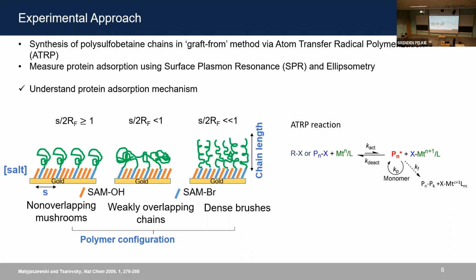So by varying the OH-terminated thiol and bromine-terminated thiol, bromine being the active part of the initiator in ATRP equilibrium, we can regulate the distances between the polymer chains, which controls the grafting density. And we can also change the chain length or the molecular weight of the polymer. And from that, we can estimate the Flory radius. We use the ratio of S/2RF in order to define the polymer configuration. So when the ratio is much bigger than 1, then you get non-overlapping isolated mushroom-like chains on the substrate. And when the ratio is much less than 1, then you have densely grafted brushes.